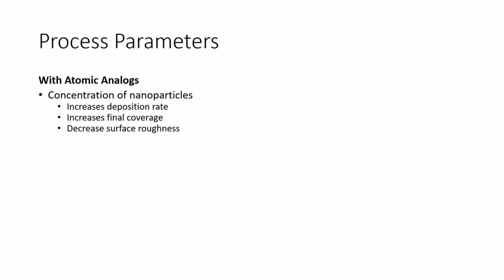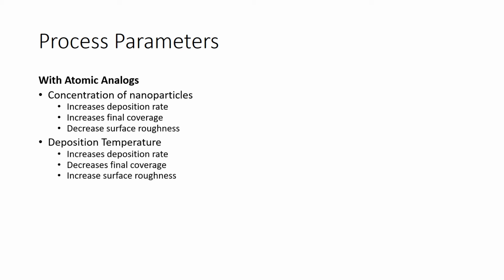Increasing the concentration of nanoparticles during deposition will increase the deposition rate, will increase the final coverage at each step, and will decrease the surface roughness of the final film. Increasing the deposition temperature will increase the deposition rate, decrease the final coverage, and increase the surface roughness.